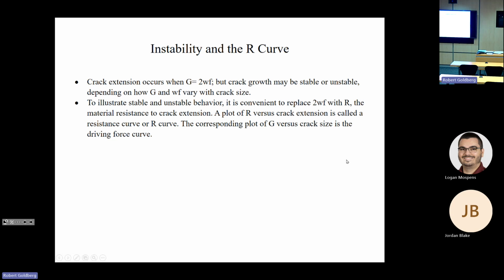So the term that was developed to represent the stable and unstable behavior, this 2 gamma_s term, was replaced with a term signified by the letter R, which is the material resistance to crack extension. And you can plot this resistance versus the crack extension, versus the crack length, and it's called a resistance curve or an R curve. And then you can also plot the strain energy release rate versus the crack size, and that's called a driving force curve.